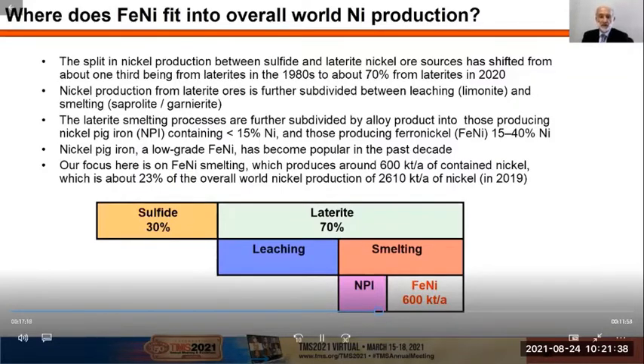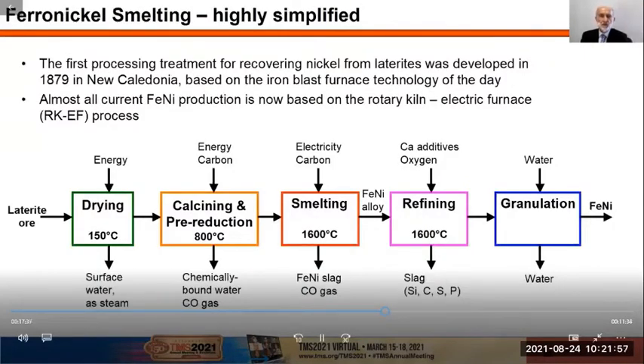Our focus here is on ferronickel smelting, which produces around 600 kilotons per annum of contained nickel, representing about 23% of the overall world nickel production of 2.6 million tons per annum of nickel in 2019 figures. The first processing treatment for recovering nickel from laterites was developed in 1879 in New Caledonia, based on the iron blast furnace technology of the day. However, nowadays, almost all ferronickel production is based on the rotary kiln electric furnace, or RKEF, process. The schematic diagram here shows a highly simplified version of the flow sheet that is employed, where laterite ore is dried using a considerable amount of energy to drive off the surface water as steam.